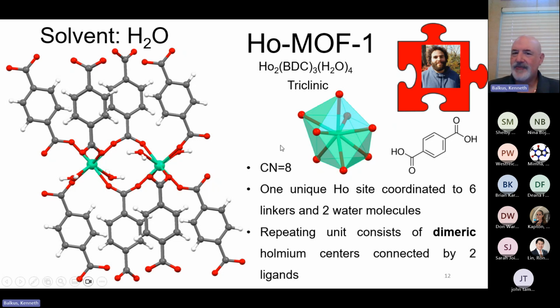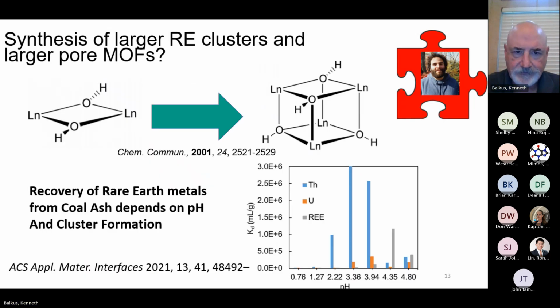Unfortunately, none of these were terribly interesting. Many of them were just dense frameworks. They had little or no porosity, and they all had these dimeric structures. So Juan says, well, some other work we were doing in the lab, we were making rare earth clusters. Maybe we can make a bigger rare earth cluster, and that might force bigger pores and be able to then functionalize it.